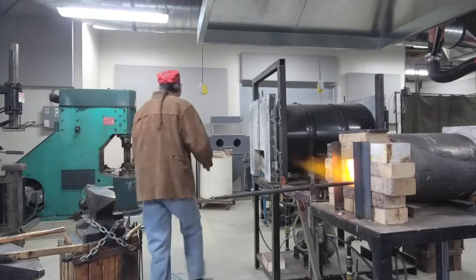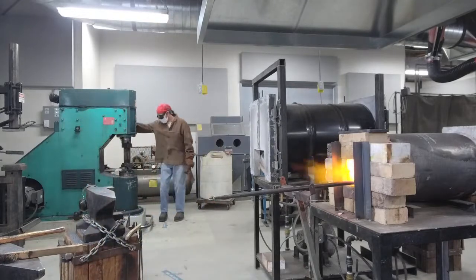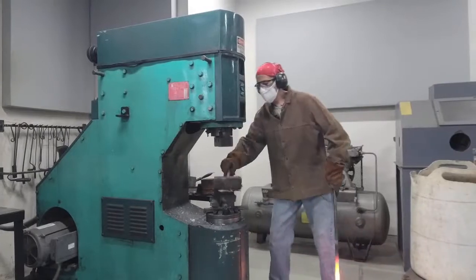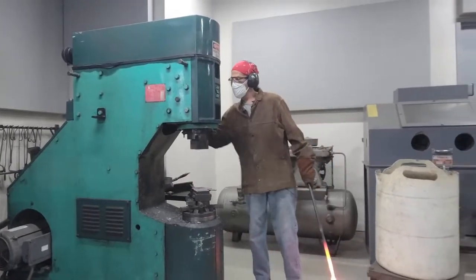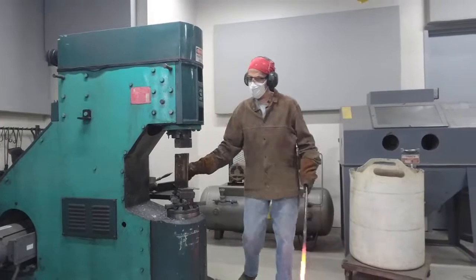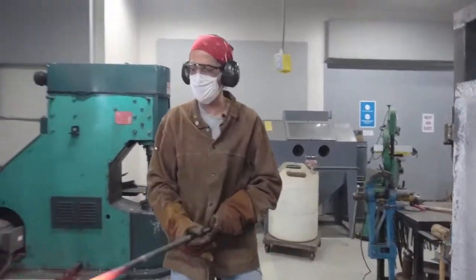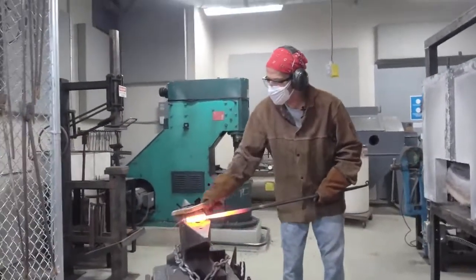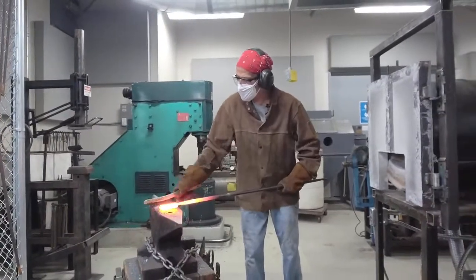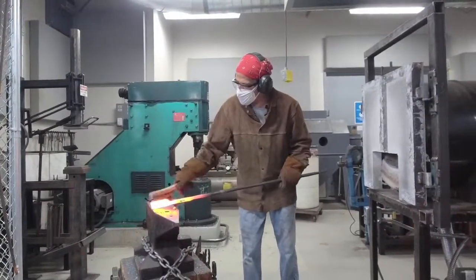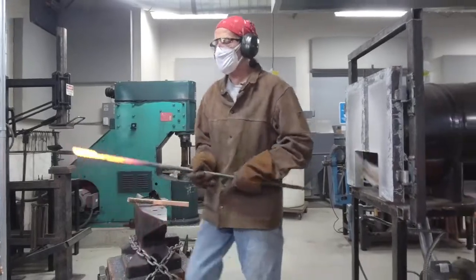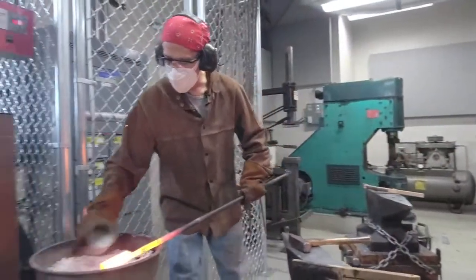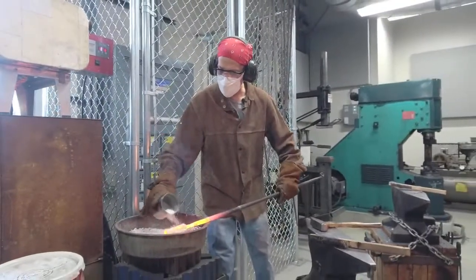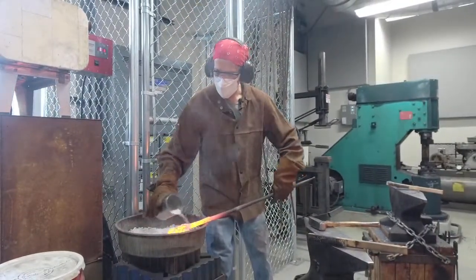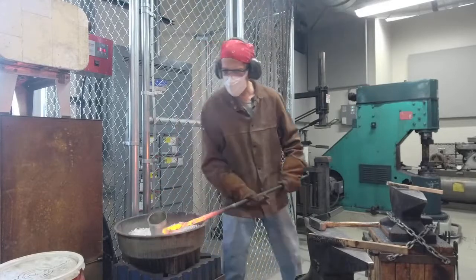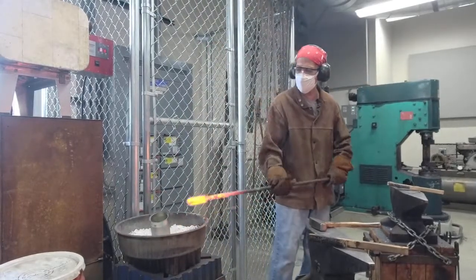Good. Is that a welding temp? Within, I'm just guessing here, say 15 to 30 seconds. Depends how large your billet is. The smaller it is, of course, the faster it cools off. But what I'm getting at is, you have to work quickly. So I have to get from the forge to the hammer quickly, do my hammering, and then after a few moments, I know it's cooled off beyond the point of welding.